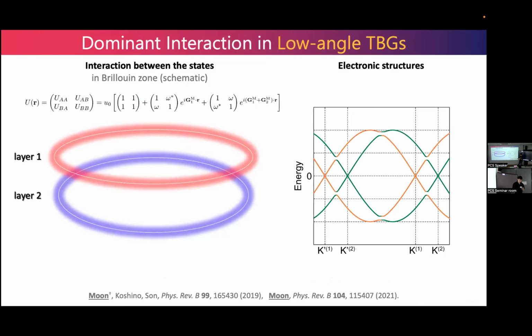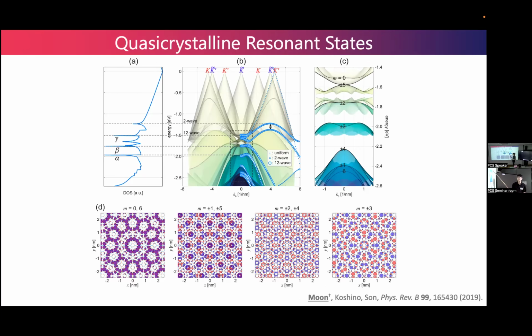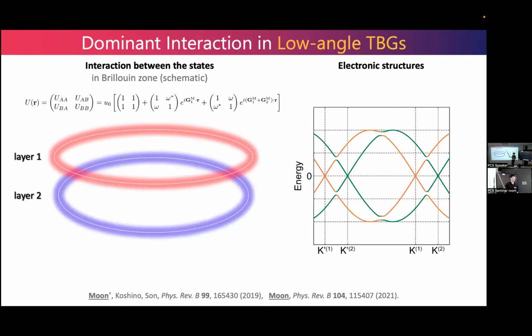So where does this quasicrystalline state come from? To show this, let's take a look at the dominant interaction in the low-angle periodic twisted bilayer graphene. This is an interlayer interaction, and you can see there are 3 terms which are associated with different wave vectors. The first term has a wave vector of 0. The second and third terms have G1M and G1M plus G2M, the reciprocal lattice vectors of the moiré superlattice. This means that a single state in layer 1 couples with 3 states in the other layer.